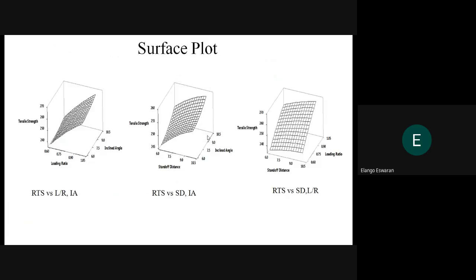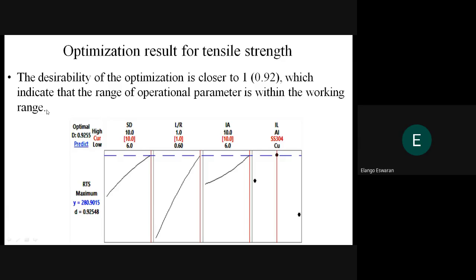Then the next one, the surface plot, shows the different parameters: the loading ratio and inclination angle, standoff distance and inclination angle, and standoff distance and loading ratio. So while increasing all three parameters, the tensile strength also increases. The optimum results for tensile strength.